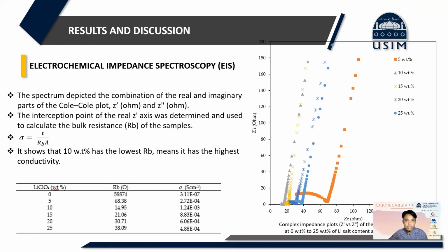First, for the electrochemical impedance spectroscopy, the spectrum depicted the combination of real and imaginary parts, the Nyquist plot. The intersection point on the real Z-axis was determined and used to calculate the bulk resistance of the sample. This is the intersection here. You can see 10% has the lowest bulk resistance. It means that it has the highest conductivity.